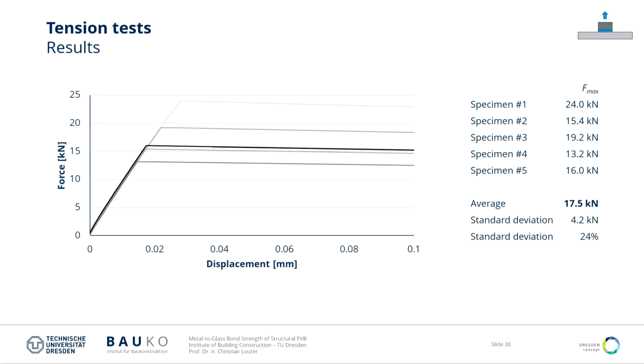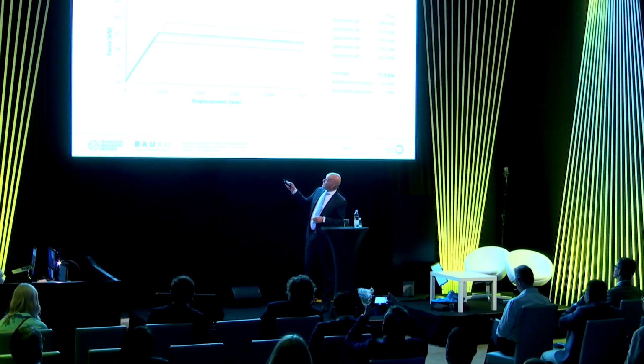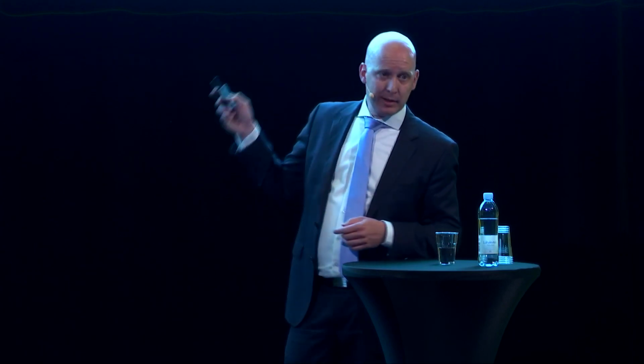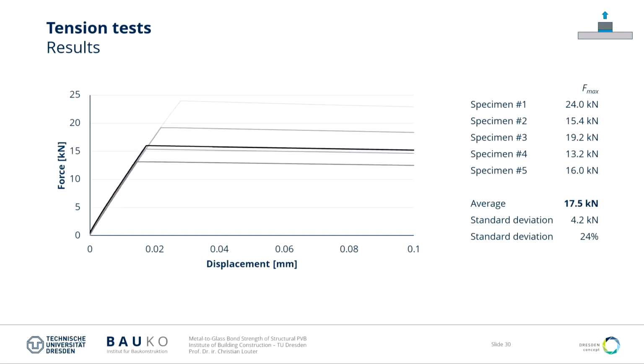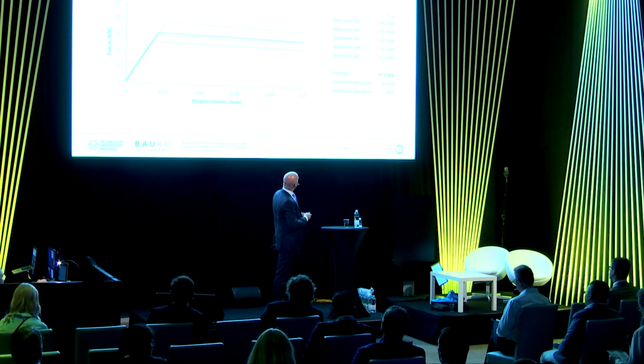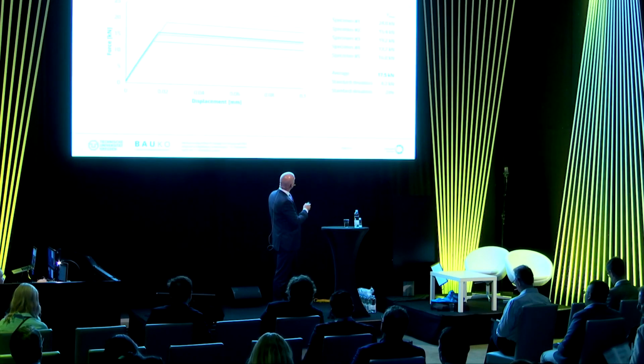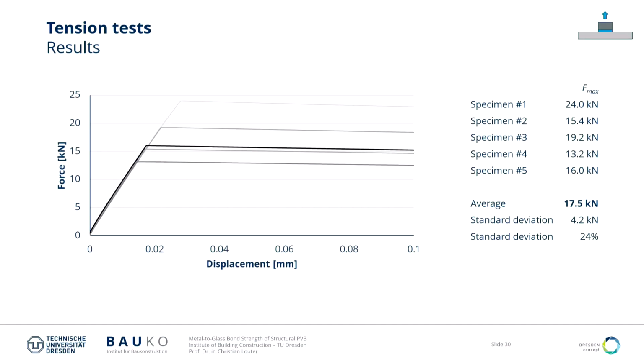These are again the results. So specimens go up until they have this ultimate failure load where they fail. This goes back to 0 directly, but the scale is so small that you don't see that it goes to 0. But this is really the ultimate load that we could apply, with an average load of about 17.5 kilonewton.